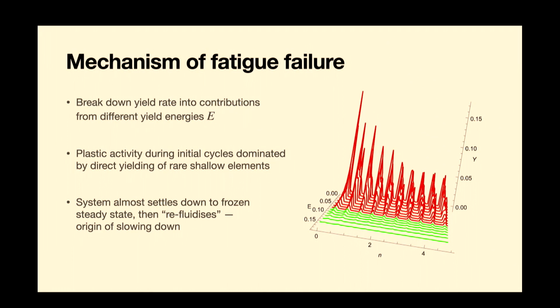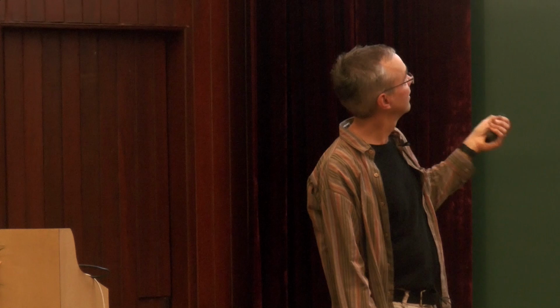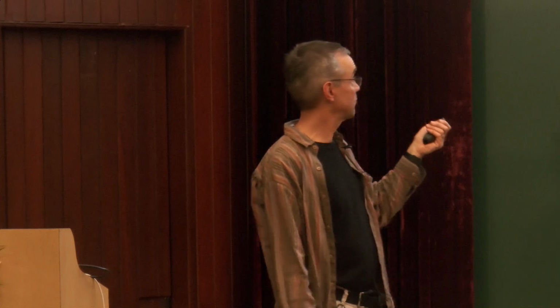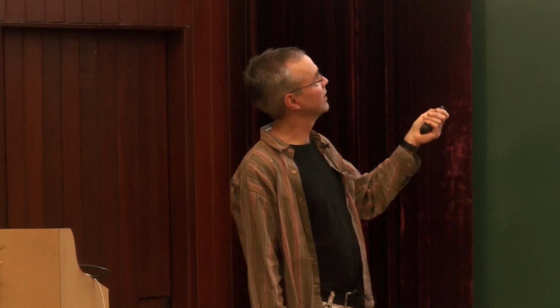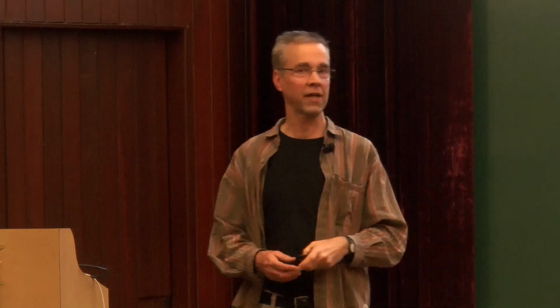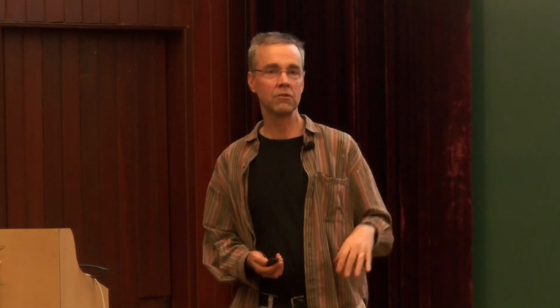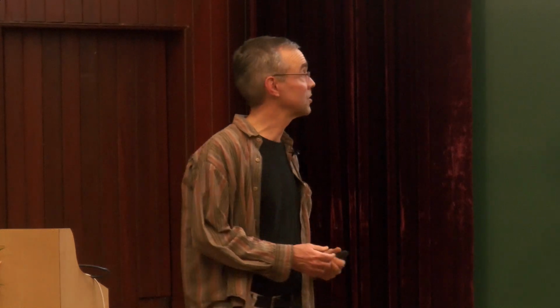And then eventually this yield rate goes down, and then gradually some of the elements with high yield energy start to yield, right? So this plastic activity at the beginning is dominated by the direct yielding of these rare elements, which have low yield energies, okay? And then what happens is that this yield rate keeps going down, as I showed you on the previous plots. The system almost reaches a frozen steady state, but then it refluidizes. Okay? So that's the origin of the slowing down in this case. So you have a dynamical transition where you more or less miss a fixed point, and then you reach another fixed point, which is the fluid one, right?